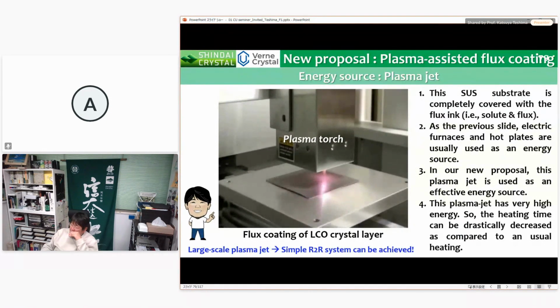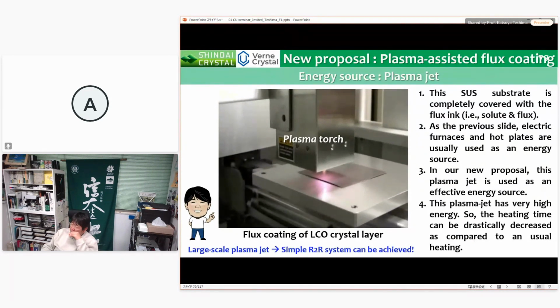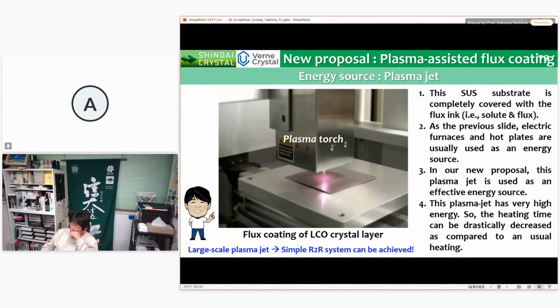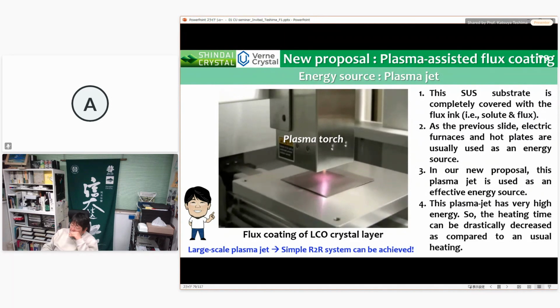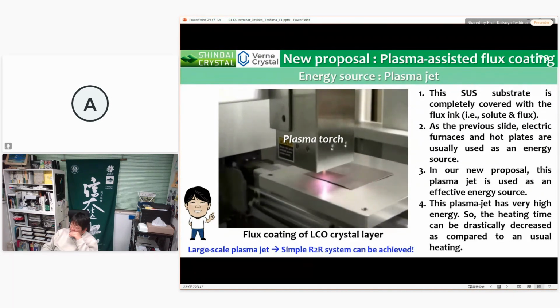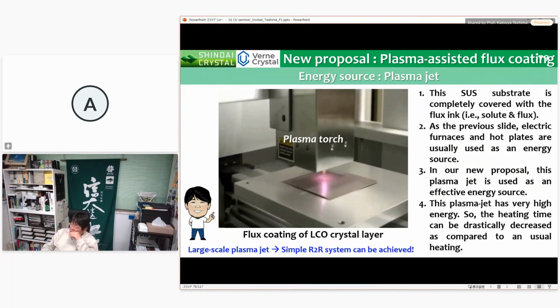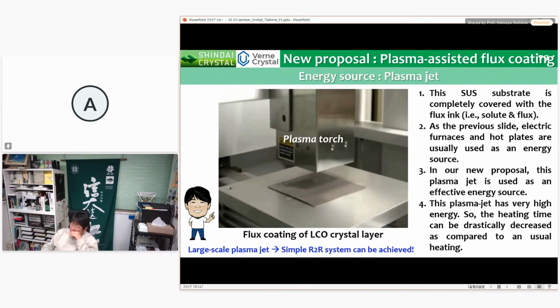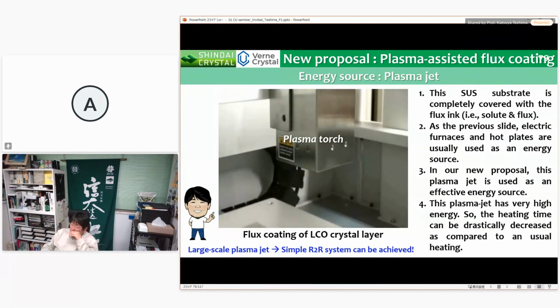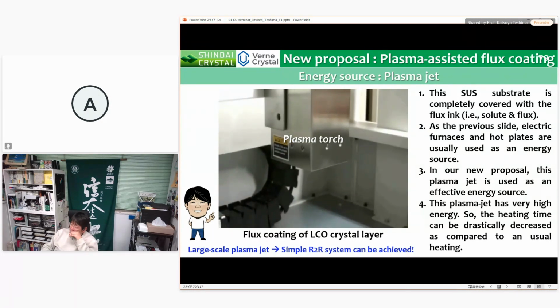This substrate is completely covered with a flux ink, that is solute and flux. As in the previous slide, electric furnace and hot plate are usually used as an energetic source. In our new proposal, this plasma jet is used as an effective energy source. This plasma jet has very high energy, so the heating time can be drastically decreased as compared to usual heating.